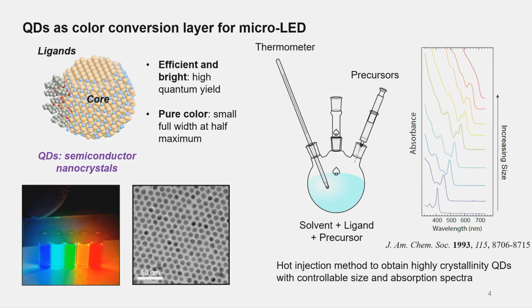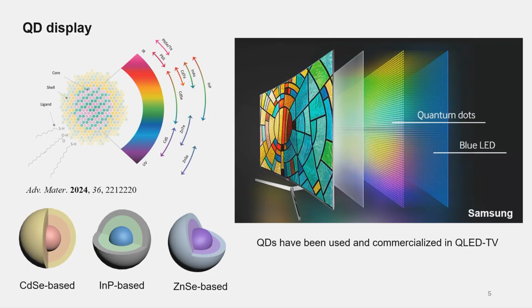Generally, we synthesize quantum dots using a hot injection method. We have a reaction pot containing precursors and ligands, you heat up to a certain temperature, and you hot inject the other precursors. In this case, we can have very precise control of the size of the particles, which gives you precise control of where it absorbs and where it emits. Using quantum dots for displays or LEDs is not a new concept. People have already developed real applications for different compositions. For example, in the early years lead or cadmium-based, and now people have shifted to more indium phosphide and zinc-based quantum dots because of less toxicity.